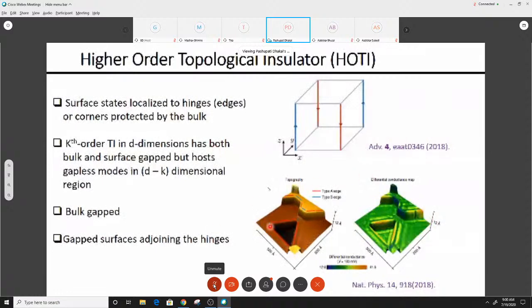So here we can see an example of a second order 3D TI, bismuth, where on the left bottom figure we can see on the cleaved surface there are two types of edges denoted by blue and red lines, and on the right figure, the differential conductance map obtained from STM measurements, we can see on the type A edges there are edge states, implying it is a second order 3D TI. So, fascinated by this, we searched for a material which potentially has this kind of novel topology and an intrinsic magnetism as well, so that we can study the interplay between the non-trivial topology and magnetism in such materials.